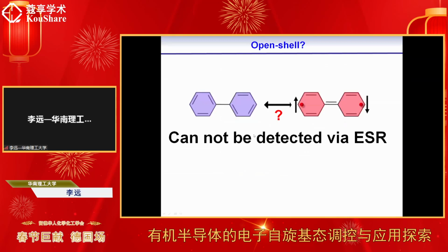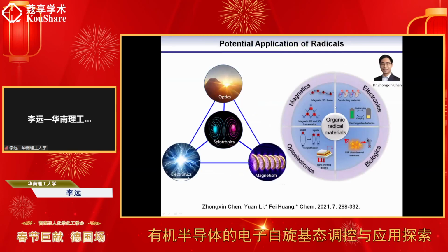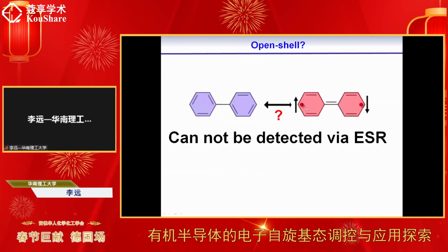And from this slide, I want to show you the two aromatic rings. This type can be donor-acceptor or the other type. And you can see if we show you the quinoid character of this type of organic semiconductors, we will get the two electrons and the two terminal groups. About 7 years ago, I proposed this mechanism. And most of the scientists in the chemistry or physics field think that it is impossible because the aromatic ring is more stable. The left resonance structure is more stable than the right one.